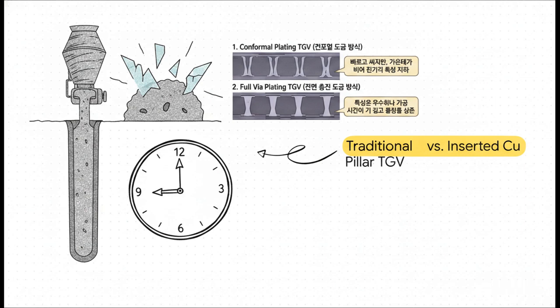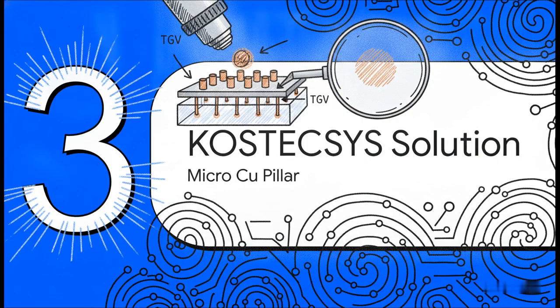And even worse, copper actually expands way faster than glass when it gets hot. So if that plated copper expands inside a fragile glass hole, the severe thermal stress will literally crack the glass right open. So how do we fix that? Enter Part 3, KOSTECSYS' micro-pillar solution.